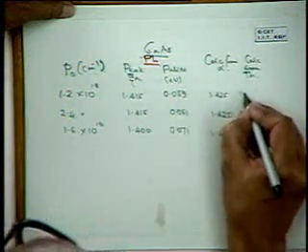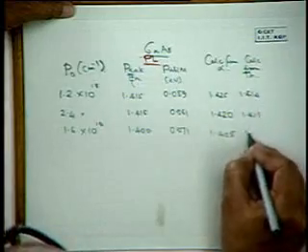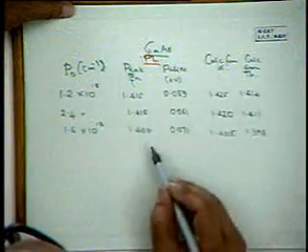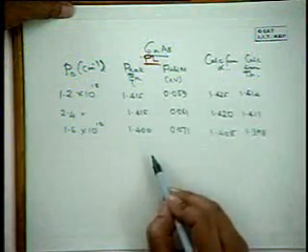This is decreasing. And if you do the calculation from the model, from theory, then this is 1.414, 1.411, 1.398. Again the exact values do not match. There is a difference of about 10 meV, but the same trend.